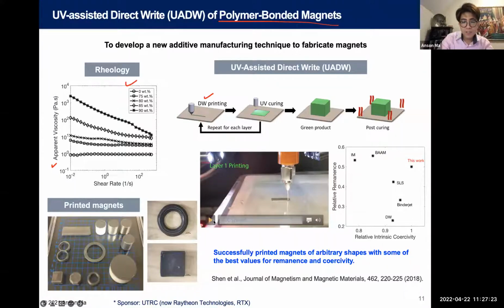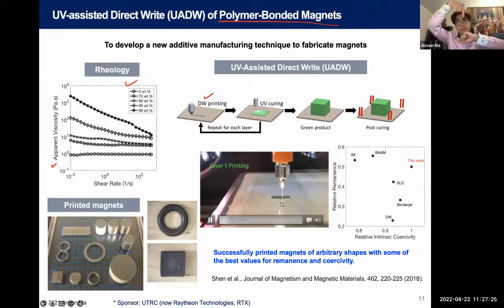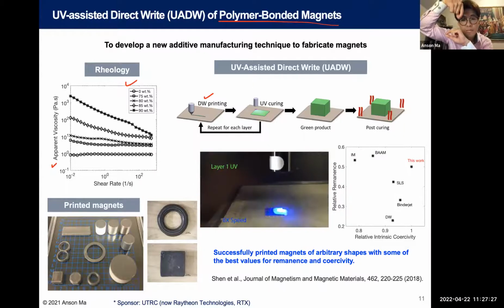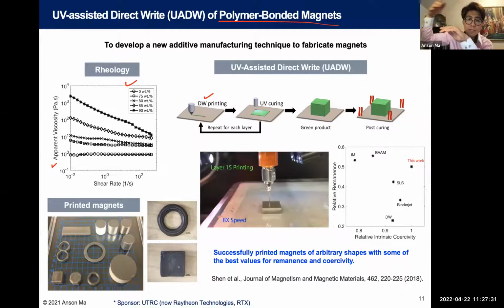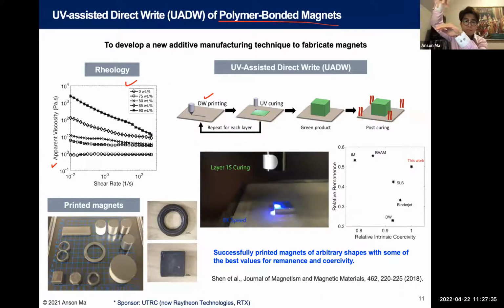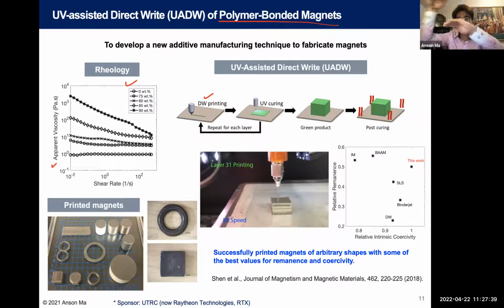And so here you see the needle. What we're dispensing is magnetic particles in the photopolymer. And after we print each layer, the UV comes and cross-links the material. So you see now there's a bright spot. This is the curing process. We keep on doing that, and we can create magnets with arbitrary shapes. And if you look at a comparison with other additive manufacturing work in the literature, we're doing pretty good. So let me explain here.